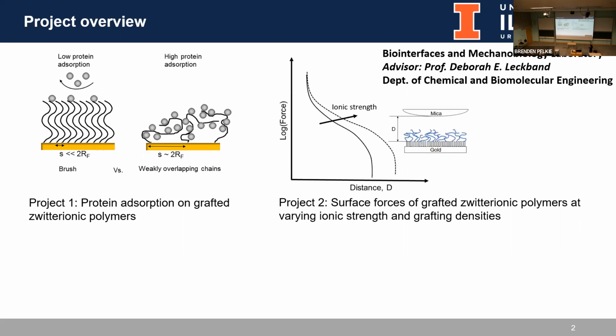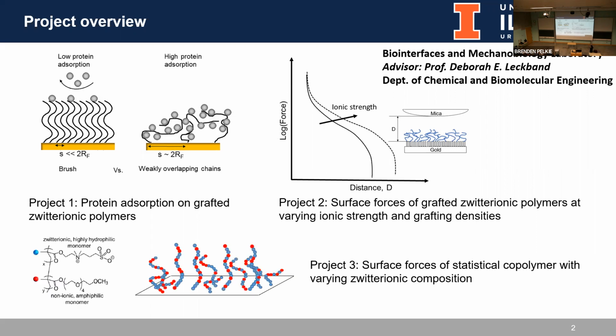The results from this study helped reconcile what we see in solution with Zwitterionic polymers as opposed to the very non-fouling properties that are commonly observed for grafted Zwitterionic polymers. In the second project, I measured surface forces of grafted Zwitterionic polymers at varying ionic strength and grafting densities. These results help to understand the magnitude as well as the ranges of distances that are important for developing nanoparticle stabilizers, for example.